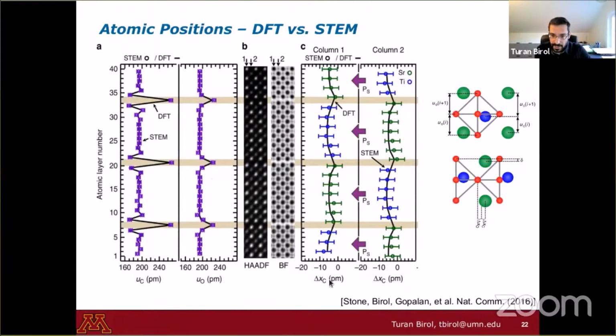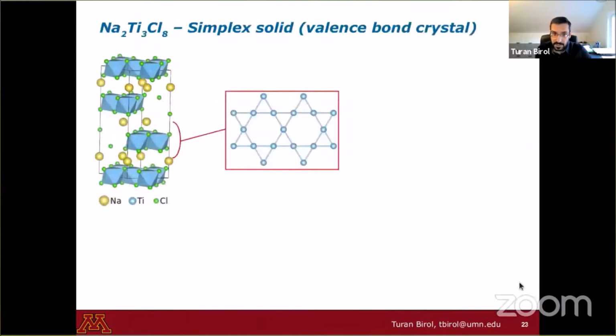And in the in-plane direction, now the scale is smaller for the displacement, so the error bars are larger. But again, there is very good agreement between DFT and the experiment. So when it comes to things like crystal structures, the point I'm trying to make is, density functional theory works surprisingly well, even with this local density approximation. And even in cases where you cannot actually capture the whole physics of what's going on in DFT, DFT can still tell you a lot about the properties of the system.